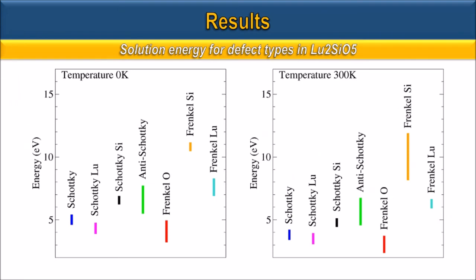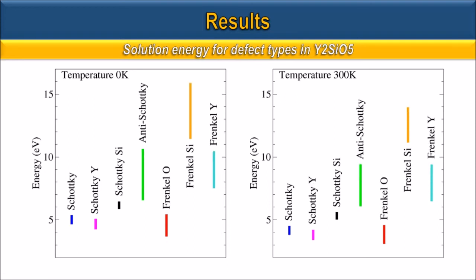So, these graphs show the range of the energies per defect for each type of unbound intrinsic defect in lutetium silicate. Results show that silicon Frenkel pairs have the biggest defect energy, while oxygen Frenkel pairs are the most favorable defect for both compounds at both temperatures. The same results were found for yttrium silicates.